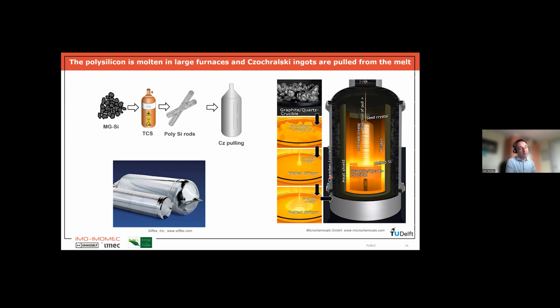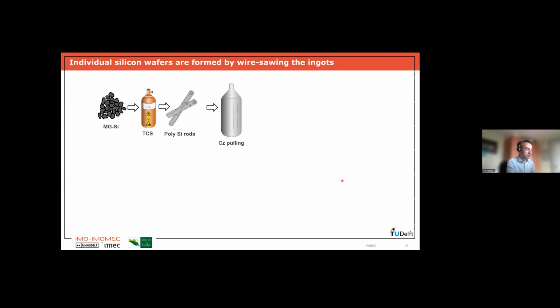Needless to say, again, because we have to use these very high temperatures and it's a very slow process, this is a very energy intensive process, which again explains the reason why we need so much energy and why it is quite costly to make these silicon wafers. So now we have very large blocks of monocrystalline silicon, very pure, with a certain dopant profile inside that we can control. We still don't have wafers.